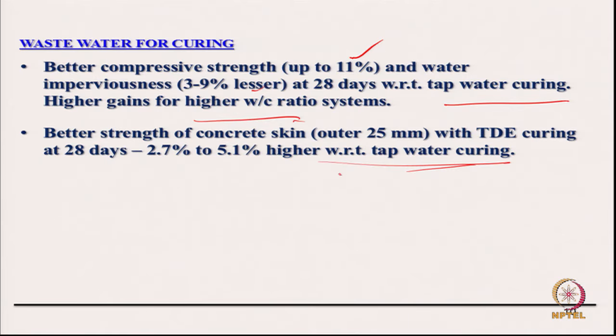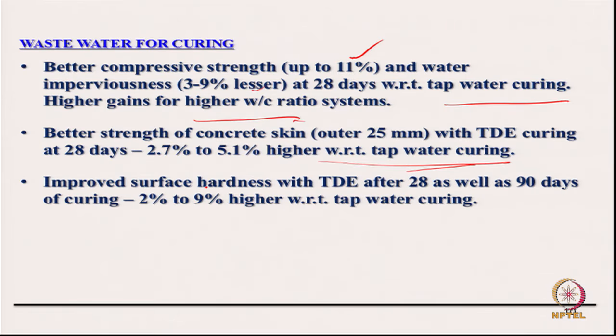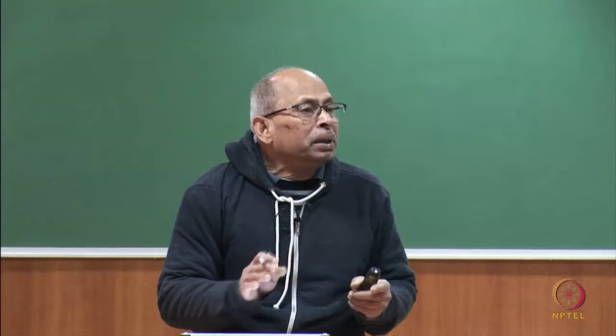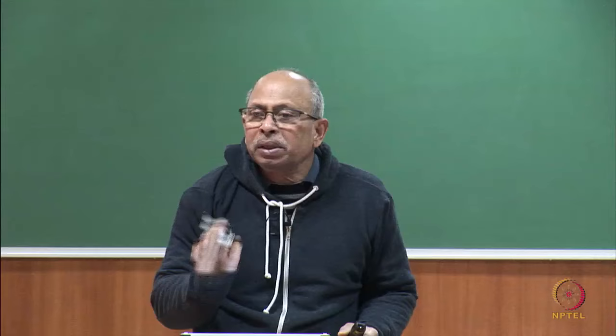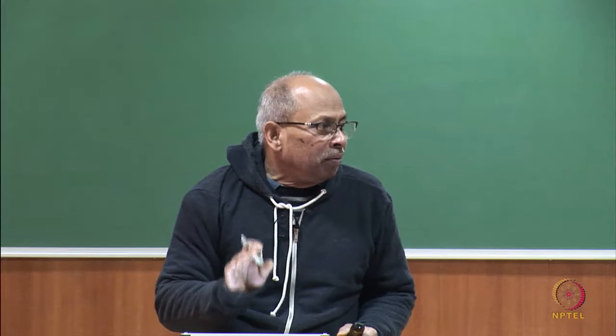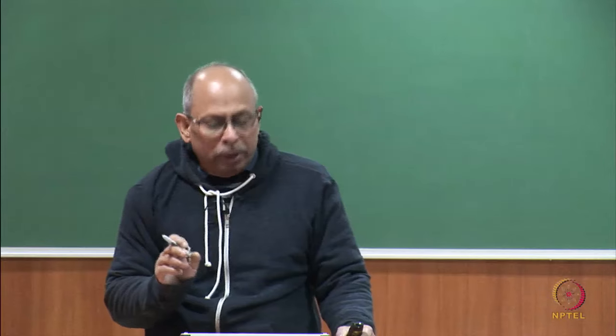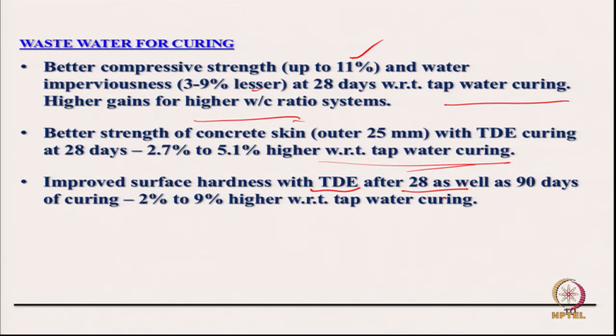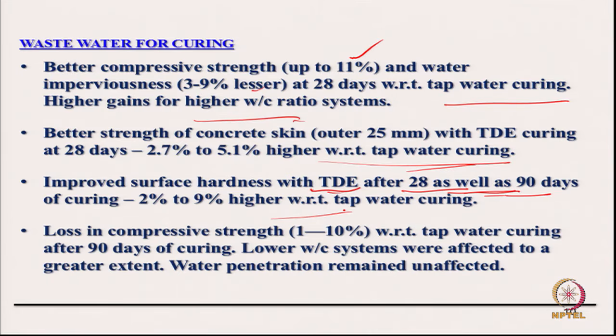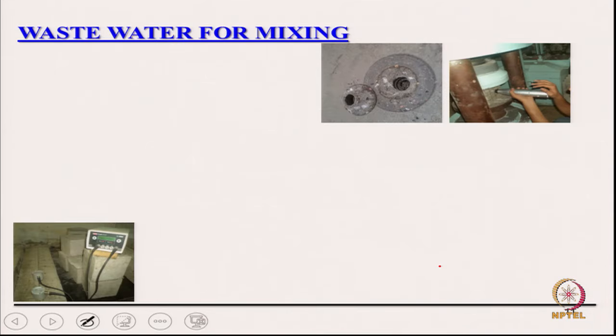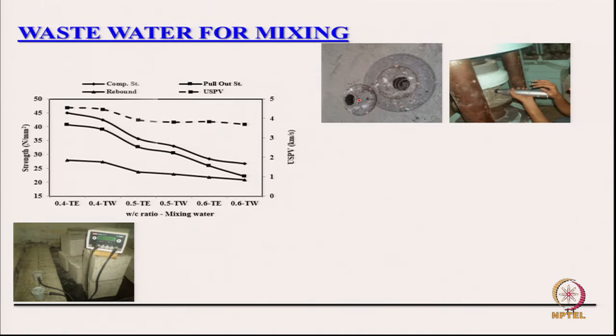This is one example of an empirical result. Somebody might say no, this is not so, but it would be within not a large variation. What we are trying to point out is that treated domestic waste, treated effluent collected from an STP, you can always use. Treated domestic effluent and 90 day strengths etc. are better. This is one case. Water penetration or all other properties of the concrete, you might find better. This is what is called a Capo test, cut from the surface. And if you look at water cement ratio, mixing water, this gives an example.